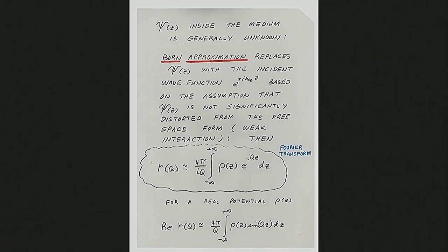And in this case, you can make an approximation such that now the reflection amplitude is equal to the integral of the scattering density multiplied by e to the i q z, where q is just k_f minus k_i, the scattered wave vector minus the incident wave vector, because we've assumed they have the same form. Well, lo and behold, this is the famous Fourier transform relationship between the reflected wave and the scattering density distribution, okay? And for most scattering, for diffraction, for example, from powders and so on, this is what works,